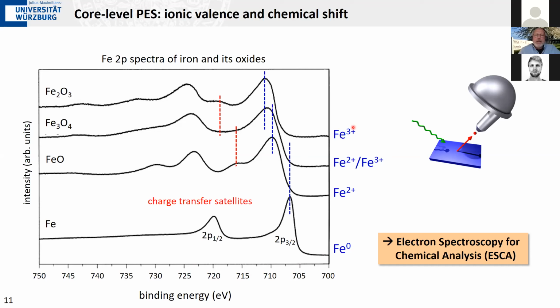And then the system can minimize energy by transferring an electron from a ligand. In this case, it would be an oxygen 2p electron that gets transferred from the oxygen 2p to the iron 3d shell, to the valence shell, in order to screen the nucleus. And this transfer costs a little bit of energy, and that can be seen here as a satellite.